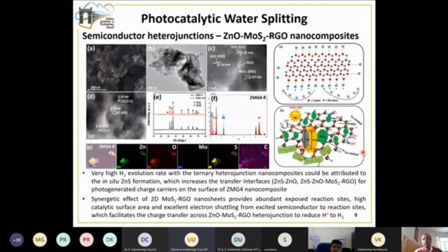Now we wanted to understand what is the mechanism, why this particular material is able to give such a high amount of hydrogen evolution. In order to understand the mechanism, we thought that we will study the catalyst which is recovered after those 4 cycles. So we took this catalyst after the 4 cycles and studied its morphology using the SEM and the TEM techniques, and studied its crystal structure using the X-ray diffraction technique, and also EDAX and elemental mapping as well.